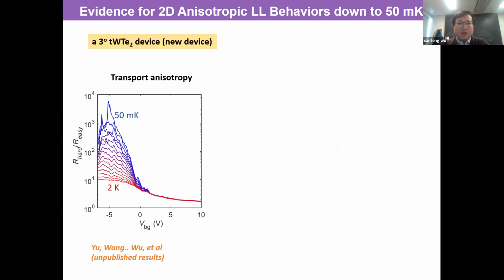In a new device near 3 degrees of twist, tungsten ditelluride, same material, but a different, smaller twist angle. The smaller twist angle means larger unit cell, so you can say a lower energy scale for the hopping term. So we see very similar phenomenon, but at lower temperature scale now. Previously in the 5 degree-ish device, at 2 Kelvin, we already see very strong anisotropy. Data showing here is the anisotropy as a function of gate voltage, but at 2 Kelvin now we don't have much anisotropy, resistance is also very low, kind of metallic. But once you cool down the device to millikelvin, the anisotropy quickly develops to more than 1,000.